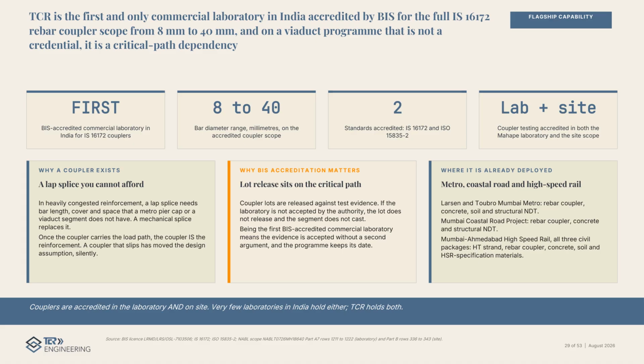This is the capability I would ask you to remember. TCR is the first and only commercial laboratory in India accredited by BIS for the full IS 16172 Rebar Coupler scope, 8 mm to 40, and on a viaduct program that is not a credential. It is a critical path dependency. Here is why. In congested reinforcement, a lap splice needs length, cover, and space a metro pier cap does not have, so a mechanical splice replaces it. Once the coupler carries the load path, the coupler is the reinforcement. Lots are released against test evidence. If the laboratory is not accepted, the lot does not release, and the segment does not cast.